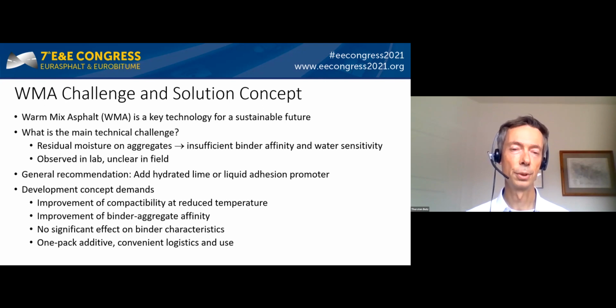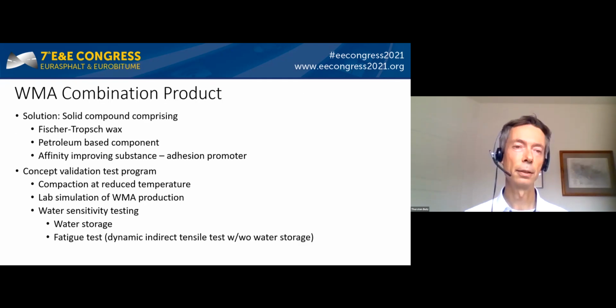Our development concept had to fulfill the following demands: improvement of compactability at lower temperature to allow warm mix, improvement of the binder aggregate affinity, and no significant effect on the binder characteristics should take place, such as stiffness and low temperature flexibility. It should be a one-pack additive, which is convenient for logistics and use. Our final solution of this development work is a solid compound comprising Fischer-Tropsch wax, a petroleum-based component, and an affinity improving substance, which can be used as adhesion promoter.